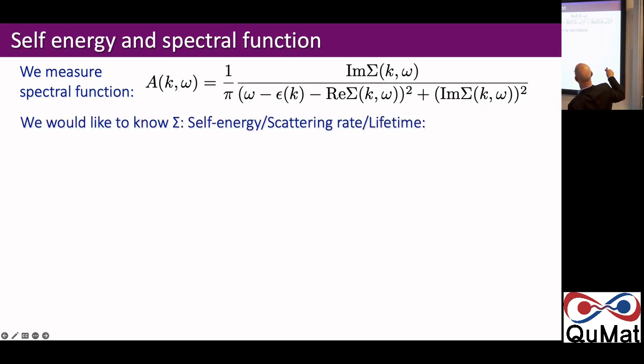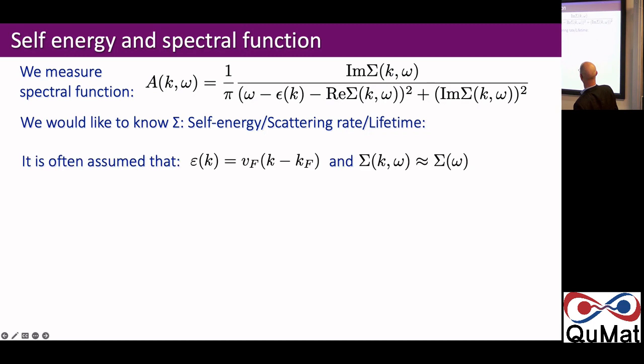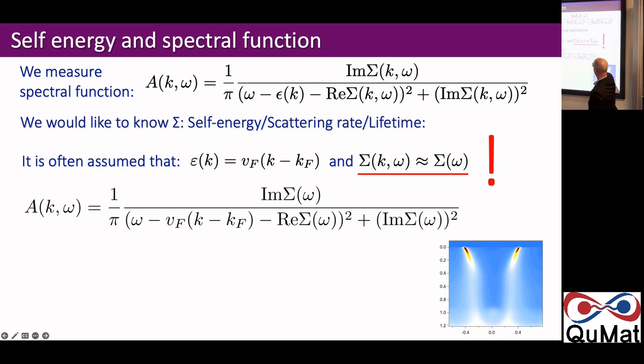Okay, so this was our self-energy, our spectral function. With this kind of form, we'd like to know what this self-energy is. And usually what photoemission people do is they say, okay, if we zoom in close to the Fermi level, then we can assume the underlying bare band, which is a crazy thing to talk about because it doesn't exist. Right? There is no bare band. But if you think, okay, I have some velocity in my problem, let's call it a linear dispersing object for the sake of argument. And let's also assume that the self-energy is dominated completely by its frequency dependence. So there's no K dependence on the self-energy. If you do those things, then what comes out for your spectral function is this thing.